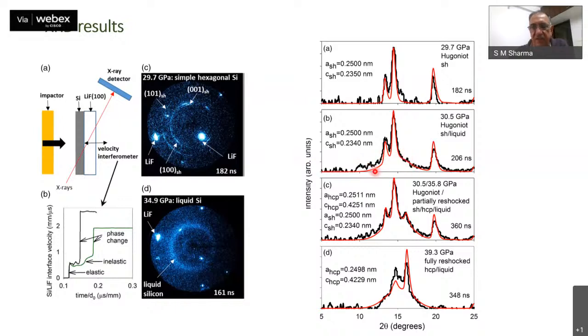This is an indication that melting is beginning to take place. At still higher pressure, this has become much broader, and so you can see there's a larger amount of melting. At still higher pressures, in fact, only this molten phase exists.